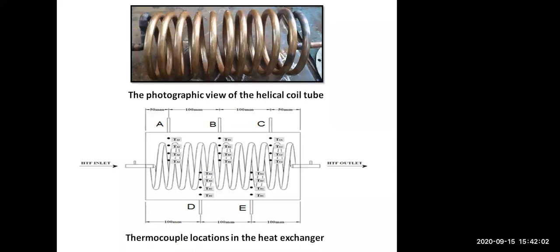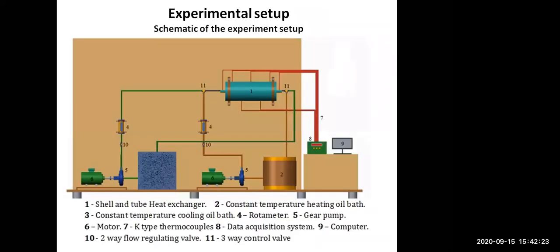Here 20 K-type thermocouples with a measuring range of 0 to 275 degrees Celsius are located in the axial direction. The thermocouples were also placed at the inlet and outlet of the tube. Then this is a schematic diagram of the experiment used for the charging and discharging experiments. So 8.5 kilogram of heat storage material was loaded into the system. The heat storage material means first we are using the simple PCM, then we are using the nano PCM, erythritol with 1% of graphene.